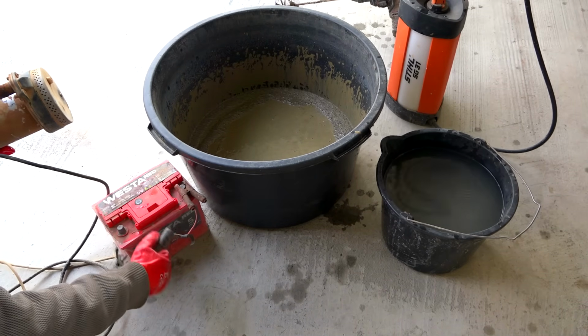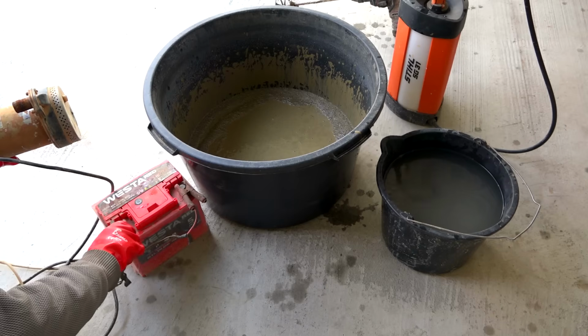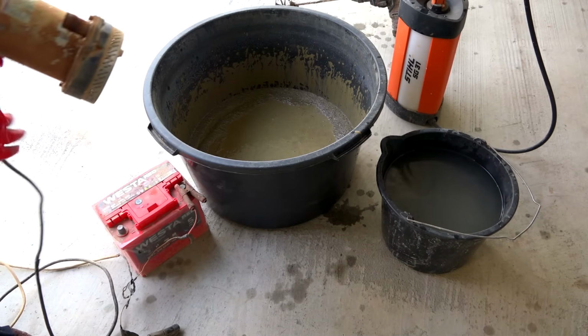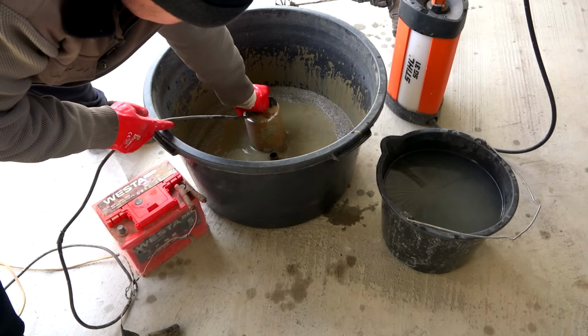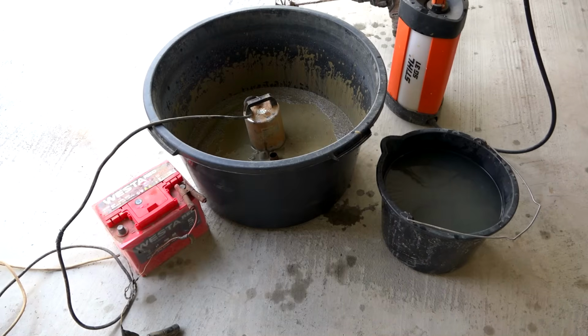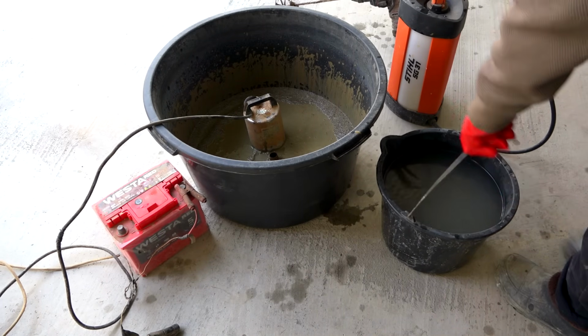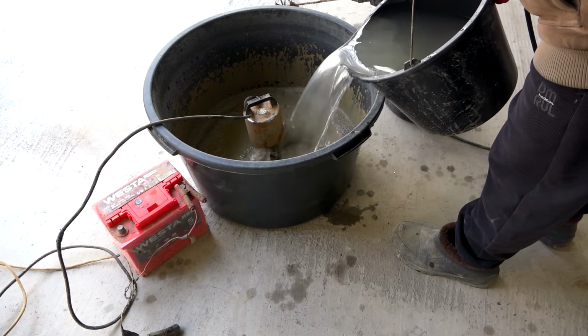Passing air through the pulp is not recommended, as it will create a lot of empty foam because air will generate large soap bubbles. I need to create the right conditions, and a water pump is ideal for intensively mixing the pulp, creating microbubbles and rich flotation foam.